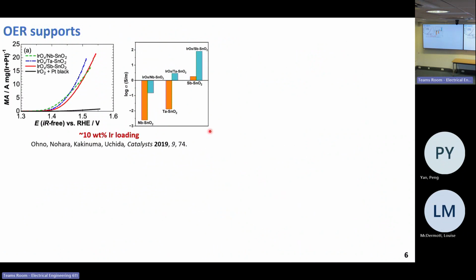Another very popular oxide to be used as a catalyst support is doped tin oxide. Dopants like niobium, tantalum, and antimony have been used to improve the conductivity of tin.